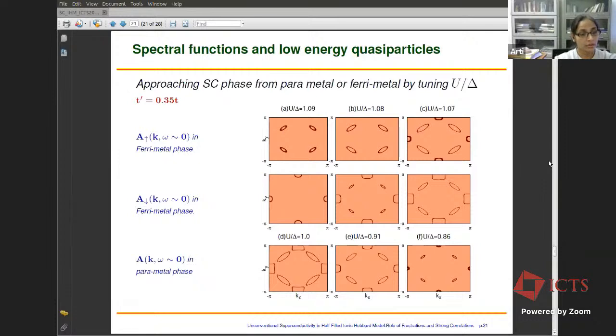So the next neighbor hopping is actually doing two things. First, it is providing a frustration against the magnetic order through the next neighbor spin exchange term, and it is also enhancing the dynamics of doublons and holes or holons on the A and B sublattices where they are allowed, and enhancing the charge dynamics and charge fluctuations.